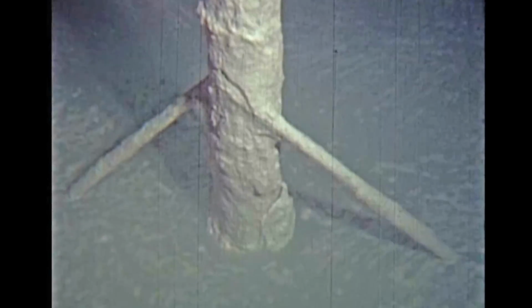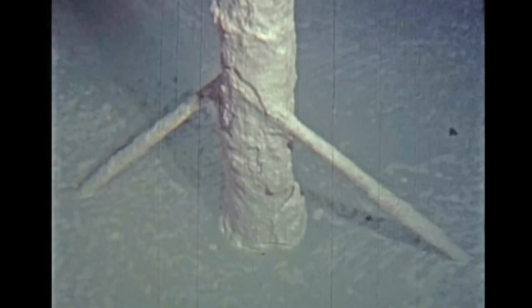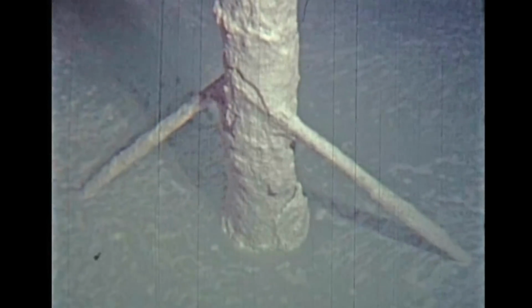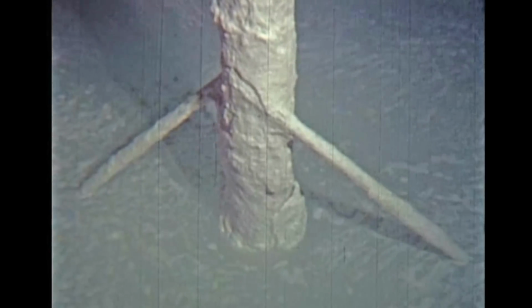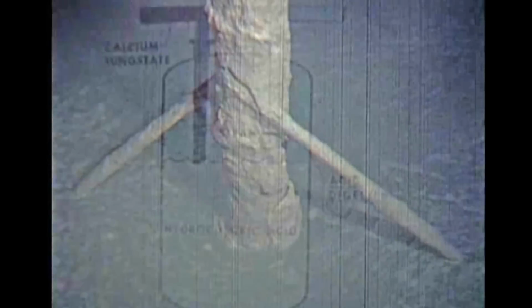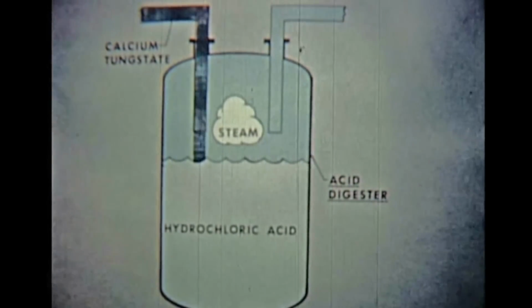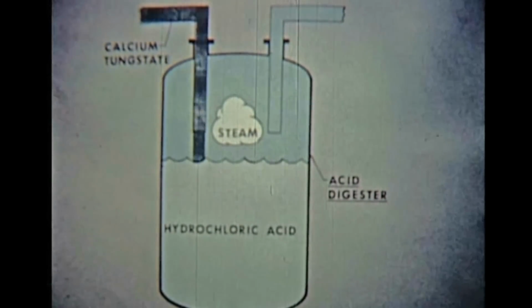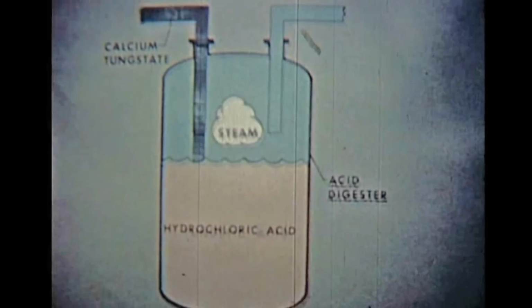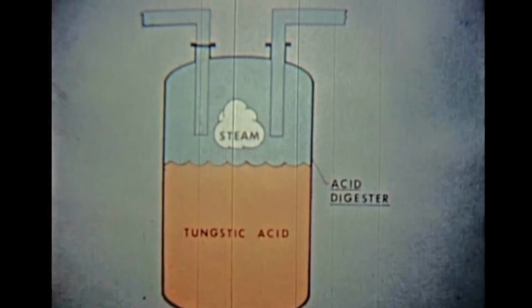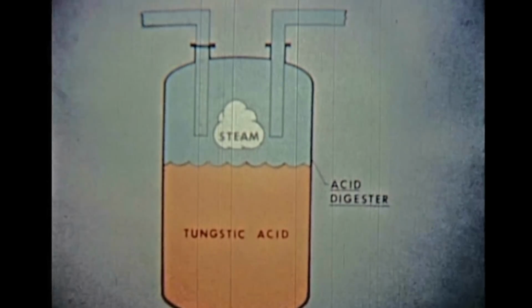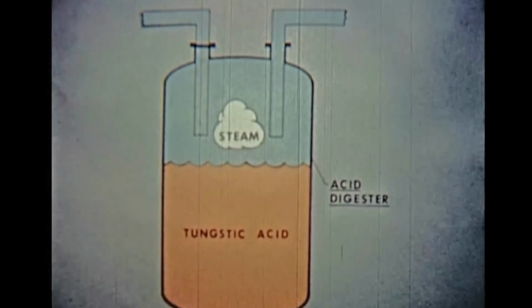A white precipitate of calcium tungstate forms. When the reaction is complete, the agitator is stopped, and the precipitate is allowed to settle for 20 hours. The liquid on top is siphoned off, leaving a calcium tungstate slurry, which is pumped into a large rubber-lined tank previously filled with hot hydrochloric acid. After the reaction is complete, the tank contains a yellow precipitate, which is tungstic acid.